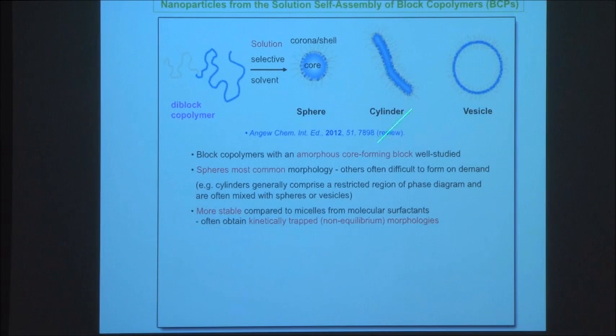The other thing to note about these structures is they're much more stable than micelles formed by molecular surfactants. So typically if you make a micelle out of a soap, for example, when you remove the solvent, they fall apart. These structures are much more thermodynamically and kinetically robust, and so you can actually remove the solvent and retain the structure. So you can think of actually doing interesting material science with these types of structures. And you can even, as I'll describe, actually make them permanent structures, fix in the structures so they won't disassemble. And this makes them, I think, very promising for a number of applications.